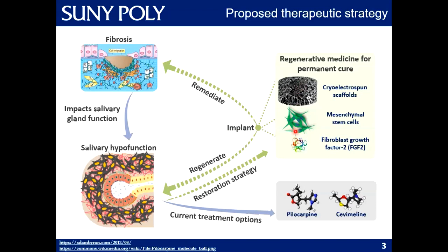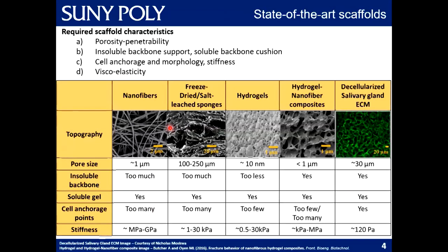The strategy we've proposed is to fabricate a scaffold which will house these MSCs, and we'll implant the cell-scaffold construct into our target site to improve engraftment, help the MSCs retain their phenotype, and also provide an empty matrix for the cells in the organ to infiltrate and regenerate part of the function. When fabricating a scaffold with properties of the native extracellular matrix, we want to ensure it has enough porosity with pore sizes on the order of 10 to 30 microns.